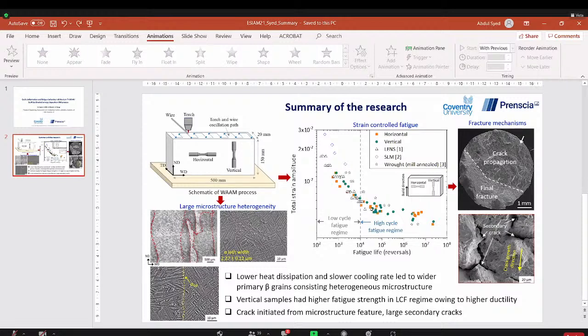We have some understanding of this anisotropy behavior, particularly the reason why horizontal samples are showing lower fatigue performance compared to vertical. We currently think that the microstructure heterogeneity along the primary beta grain boundary, which has either colony or basket weave microstructure, and is also spatially changing within the gauge length of the sample, is one of the sources. Whenever the material is loaded along the horizontal orientation, this primary beta grain boundary is acting as a weaker interface.